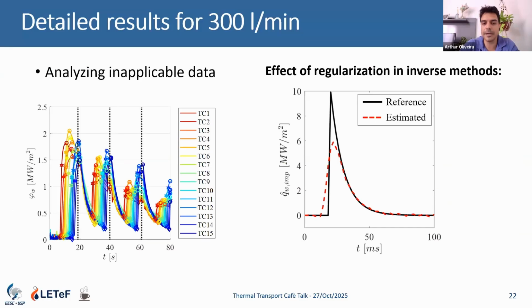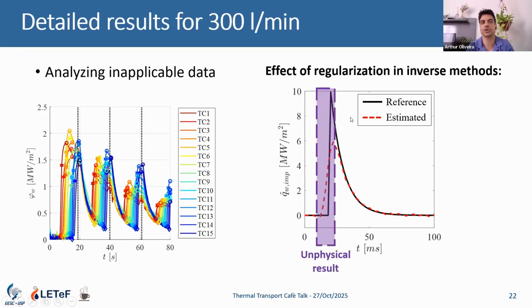For instance, let's say this is a simulation here, heat flux over time. Let's say I want to estimate the heat flux profile evolution as the black line. When I apply my inverse method, there is this regularization that causes a kind of penalization, a degradation in the heat flux estimate to stabilize the calculations. So this part of the calculation, where we see this increase and then this loss of the peak, is not physical. This is a mathematical feature of the method, so it's not a reliable result.